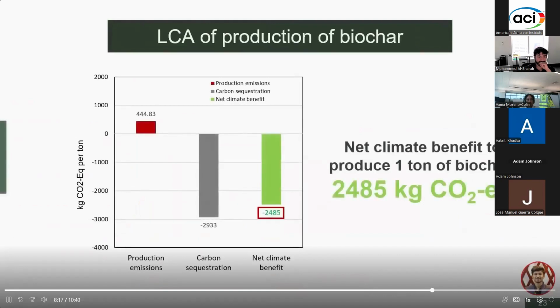To produce 1 ton of biochar, 444 kg carbon dioxide equivalent will be generated. It seems a pretty high value, though it is actually not, because as the biochar can sequester carbon, the net climate benefit is more than 2400 kg carbon dioxide from the production of only 1 ton of biochar. So producing biochar is good for the environment until we allow it to decompose.